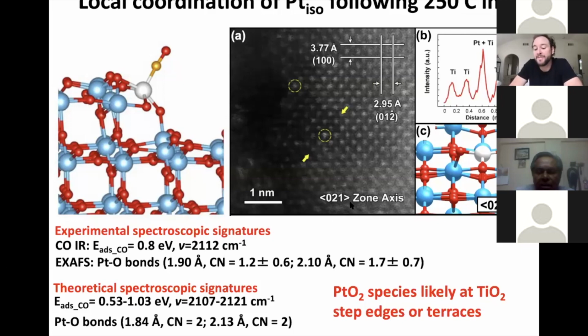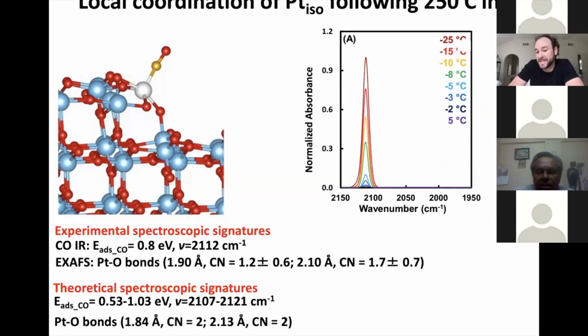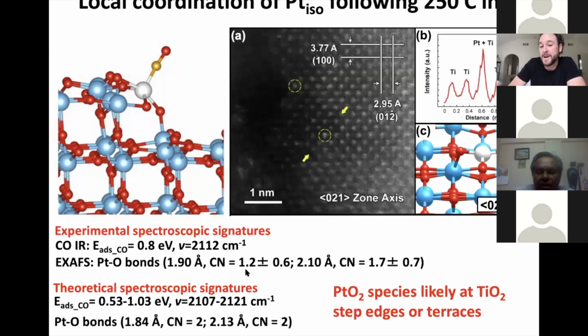So now we have, from infrared, a statistically significant measurement telling us that spectroscopically we have similar species to the DFT calculation. And we have visual evidence that the coordination environment looks the same for the theoretically proposed system compared to this. So from this, we would conclude we're doing a good job of identifying the environment of this site. But we could only justify this because we had uniform species.